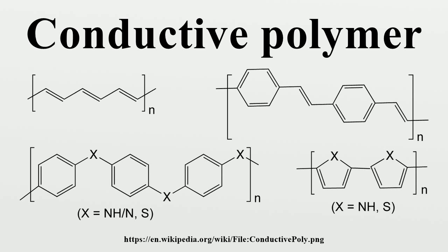Generally, it is assumed that conductivity should be higher for the higher degree of crystallinity and better alignment of the chains. However, this could not be confirmed for polyaniline and was only recently confirmed for PEDOT, which are largely amorphous. Properties and applications. Due to their poor processability, conductive polymers have few large-scale applications. They have promise in anti-static materials and they have been incorporated into commercial displays and batteries. But they have had limitations due to the manufacturing costs, material inconsistencies, toxicity, poor solubility in solvents, and inability to directly melt process.